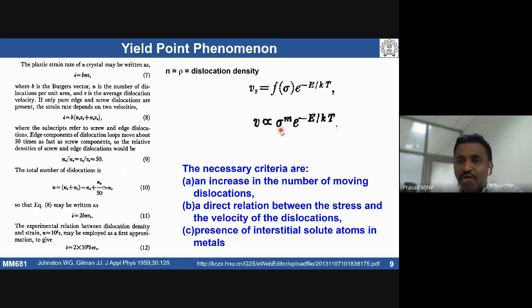So if we talk about Cottrell theory, we are talking about carbon and nitrogen atoms, which are interstitial atoms that can actually lock the dislocations. So how many solute atoms are required? What is the fraction of carbon atoms needed to pin a certain number of dislocation density? How much carbon content is needed? Why do you say only low carbon? Why not high carbon? And within low carbon, how much carbon content is responsible for such a yield drop in the material?